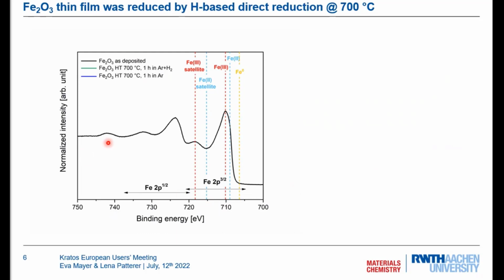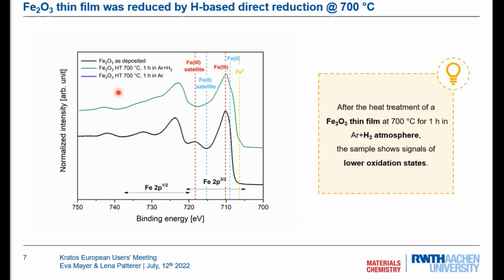And this line corresponds to the thin films without any reduction experiments. And as you can see, it nicely corresponds to the iron 3 oxidation state peaks, and also the satellite one. After reducing it at a temperature of 700 degrees Celsius for 1 hour in argon and hydrogen atmosphere, you can see that a shoulder is formed here corresponding to the iron 2 oxidation state peak, and also the satellite is visible. Even a little peak for metallic iron is visible. Therefore, we have definitely reduced our sample.